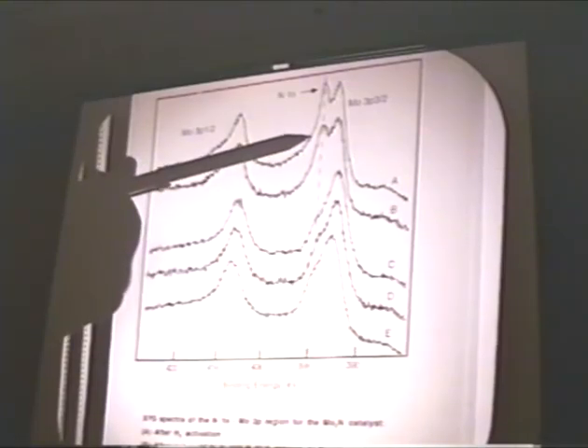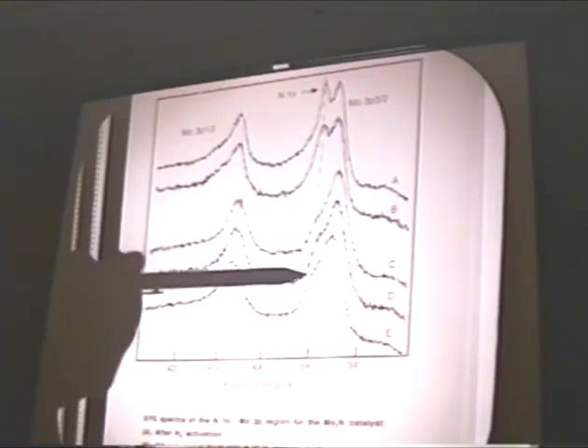by doing some post-reaction characterization. What I'm showing here in this first view graph is the nitrogen 1s XPS spectra for different catalysts. Again, the spectra have been taken without exposing these catalysts to atmosphere using a controlled atmosphere stage of the XPS system that we have. We're starting out with freshly activated catalyst and then moving down with catalysts which have gone through different reactions. The first one is HDN reaction only, and then we have other reactions which have either simultaneous HDN, HDS presence, or H2S in the feed, or this is benzothiophene HDS, but there is also ammonia present.